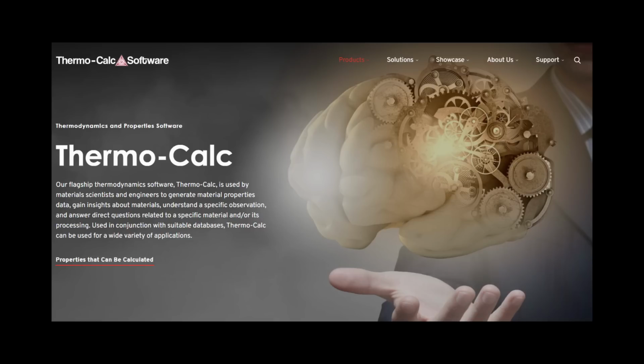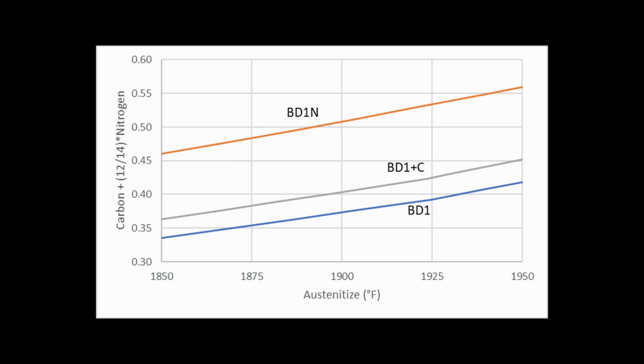Like, okay, with that much carbide and that much carbon in solution, I can probably get around 63 Rockwell as quenched, and I'll have around this much wear resistance. It doesn't tell you, oh, this will make a great knife steel, but you can use other bits of knowledge that you have, other studies that you've done, like carbon versus hardness, and make some predictions about properties of steel. In this case, we're only making relative comparisons. We see that BD1N has more carbon and nitrogen in it than BD1, so we would probably expect it to have more hardness.